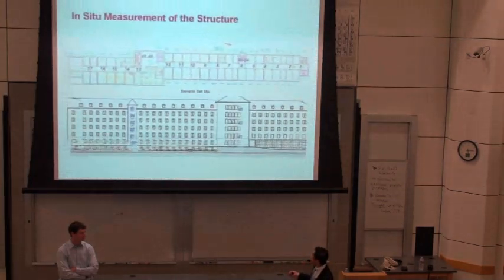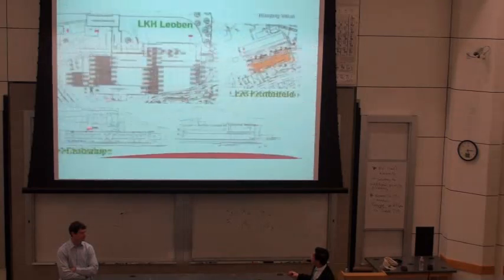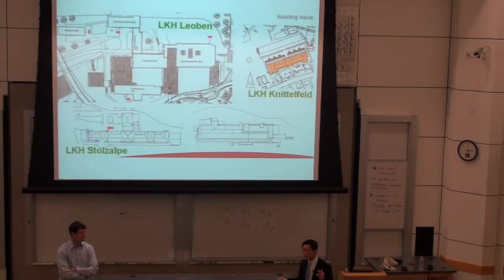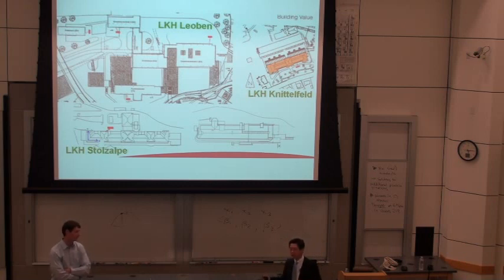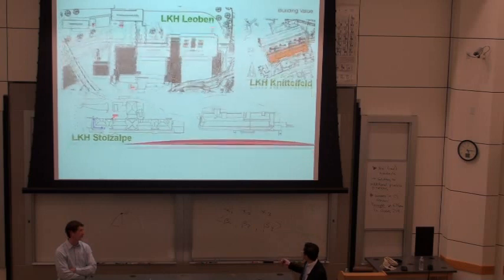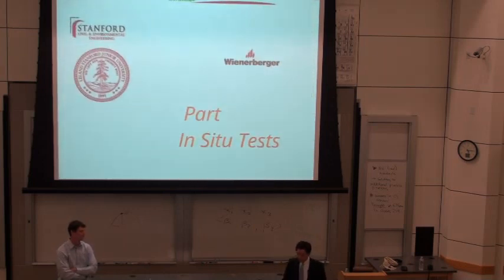In codes, in general, for unreinforced masonry, you have values in Europe somewhere around 2. Just in Italy, in the Ordinanza, Magenes has defined the OSR, as I said, the overstrength factor, with somewhere around 1.4 to 1.5. You can have up to 3. But these are just experimental values in order to show what is possible with masonry. For sure, if it's applied in a code, it's much more conservative.